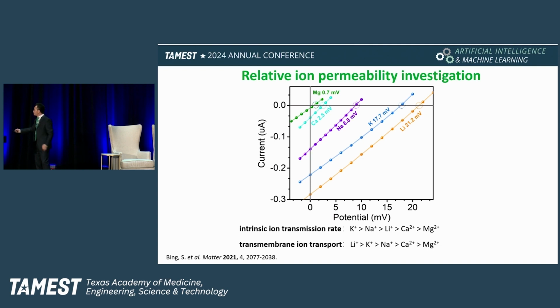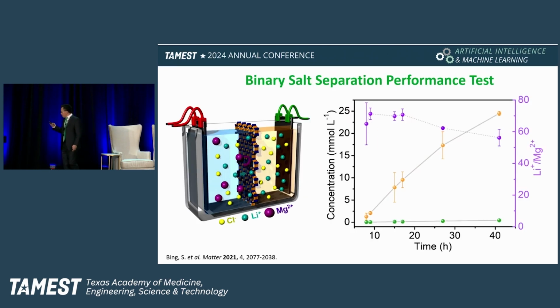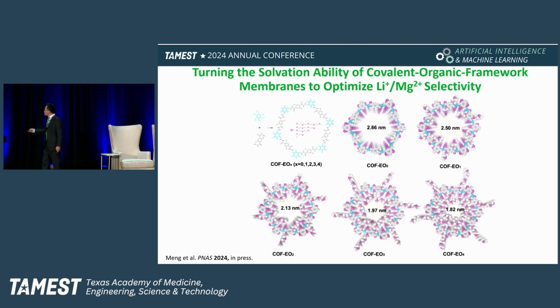For the transmission rate, potassium is the fastest, okay? And then we can reverse it. Lithium is the best, followed by potassium, sodium, calcium, and magnesium. And we can separate them. Also, we made a device where we can achieve a lithium and magnesium selectivity of over 70%. So this is our recent work.